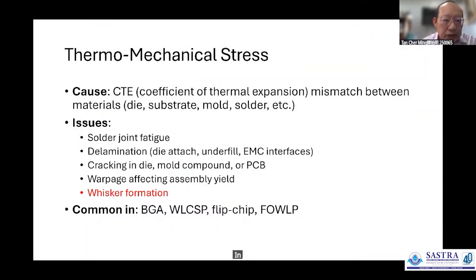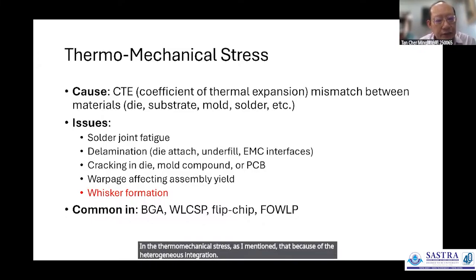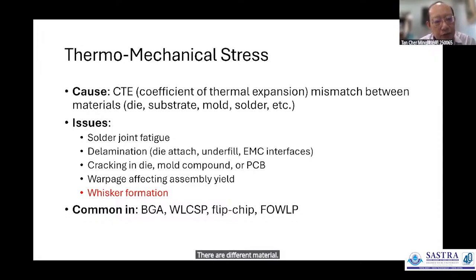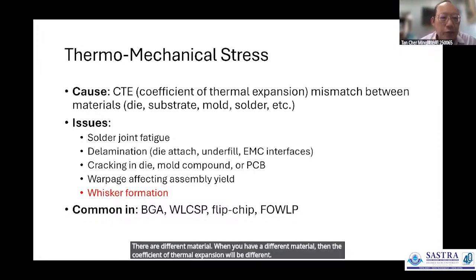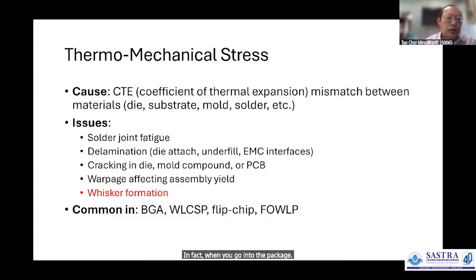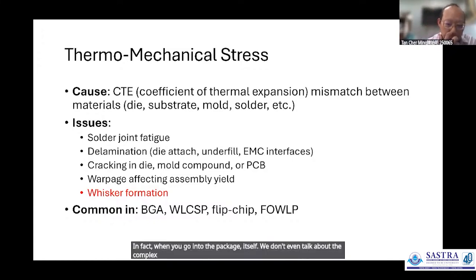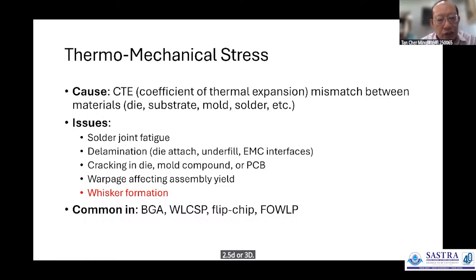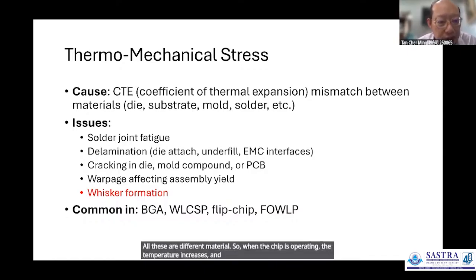In the thermomechanical stress, as I mentioned, because of the heterogeneous integration, there are different materials. When you have different materials, then the coefficient of thermal expansion will be different. In fact, when you go into the package itself, we don't even talk about the complex 2.5D or 3D. We have a silicon die with a substrate, with the molding compound, which is a polymer, and we have solder. All these are different materials. So when the chip is operating, the temperature increases and therefore there will be CTE mismatch.